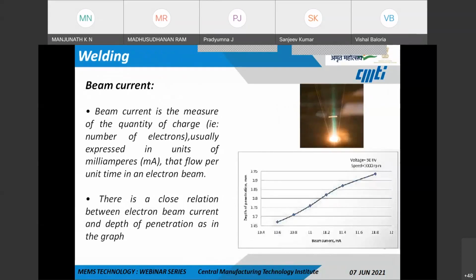So the next parameter is the beam current. The beam current is a measure of the quantity of charges, that is the number of electrons, usually expressed in milliamperes, that flows per unit time in an electron beam. It basically defines the electron flux which is passing at the beam spot. So there is a close relation between the electron beam current and the depth of penetration as well. This graph also gives a better idea of how the beam current will dictate the depth of penetration of the material.